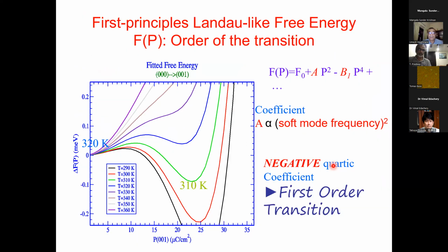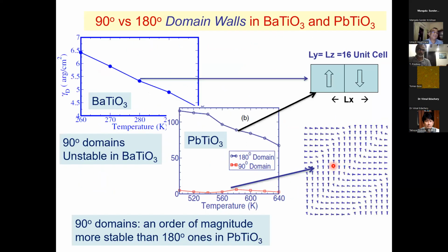So once we have simulated phase transitions, we also have access to domain walls, which are very important for technological applications, because when you make devices or memories, you basically want to be able to switch the direction of polarization. So we simulated domain walls in these two oxides, and look at this, what a contrast between barium and lead titanate.